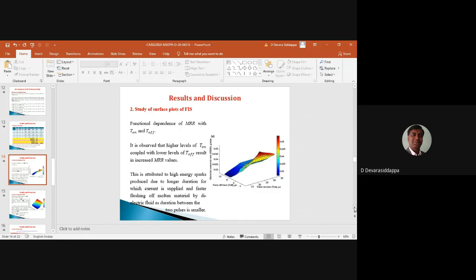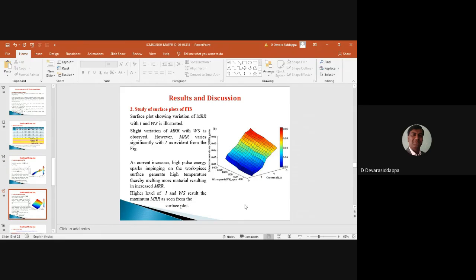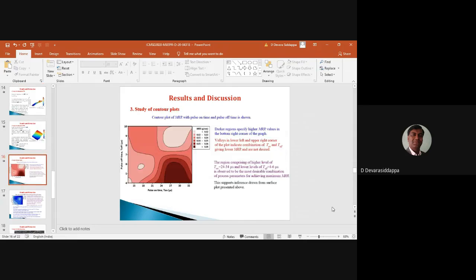And this shows the surface plot of MRR with respect to current and wire speed. As you can see, the variation of the MRR with respect to wire speed is very slight, whereas a steep variation in MRR with respect to current is observed. As current increases, high energy pulses are generated that impinge on the workpiece, generating more heat and hence higher temperature, thereby melting more material, which results in higher MRR. Higher values of current and wire speed are found to result in higher MRR, as you can see from this plot. The contour plot is also studied.